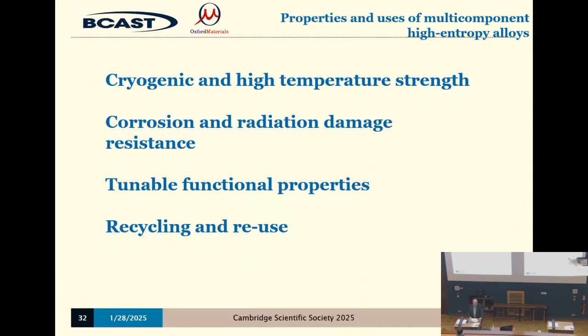So to summarize, the Cantor alloy itself, the range of Cantor alloys, the face-centered cubic ones, have the best low-temperature cryogenic properties, strength properties of any known material. Some of the BCC ones are called Senkov alloys now, after Oleg Senkov, have some of the best high-temperature strength properties known. There's tremendously good corrosion, radiation, damage resistance. If you take these compounds, which have only much more recently begun to be studied, they have tunable properties, tunable by composition, which has never been possible before. We've always used pure single crystals of things. So piezoelectric materials, or solar energy converting materials, or battery materials, we can tune them by tuning the composition, and that's really a great freedom.